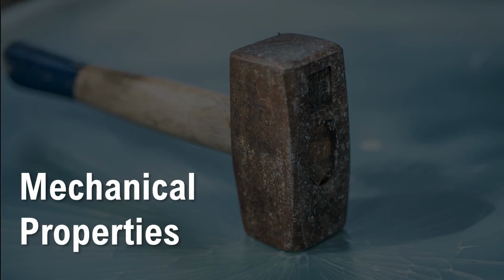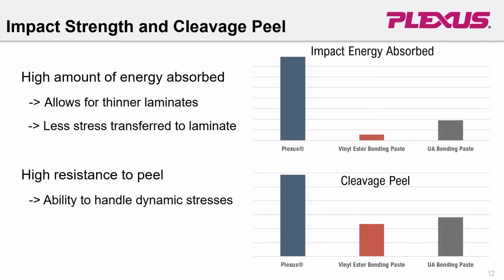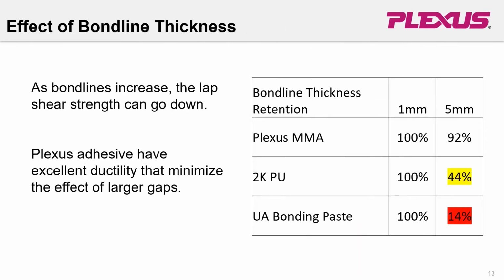Next, let's talk a little bit about mechanical properties. So here I have a vinyl ester bonding paste and a urethane acrylate bonding paste that we've tested with various types of tests besides lap shear. So we looked at impact energy absorbed, and Plexus absorbs much more energy in impact, which means less stress is getting transferred to your laminate. It also has high resistance to peel. So cleavage peel, used for thicker laminates, Plexus does much better than these other two joining pastes.